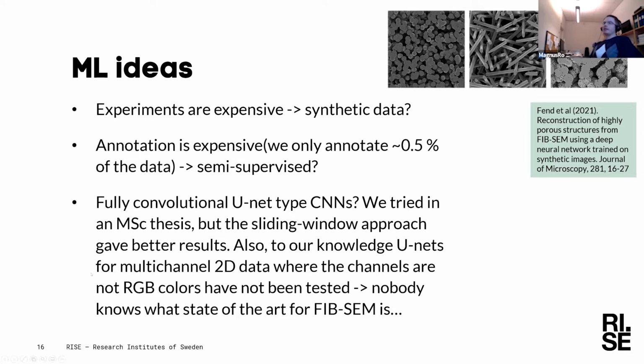Another thing is that the annotation is very expensive. In this data set that I talked about, we only annotated about 0.5% of the entire data, and it still took a couple of days for the imaging expert to do that. So the question is if there are semi-supervised approaches where we could somehow utilize all the unsegmented data for the training of the CNN. And the third one was what I already mentioned, that we tried fully convolutional U-Net type CNNs. It feels like it should be better, but from what we have seen, it appears they are not. But I regard it as an open question, and with the right design, it's possible that it could be better. But it's an open question for now.